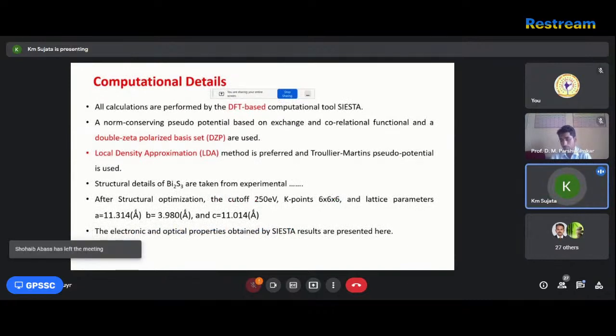This is the computational details. Here I use the DFT based computational tool SIESTA, with norm-conserving pseudopotential based on exchange and correlation functional and double zeta polarized basis set. I also use the local density approximation method, and the Troullier-Martins pseudopotential is used.